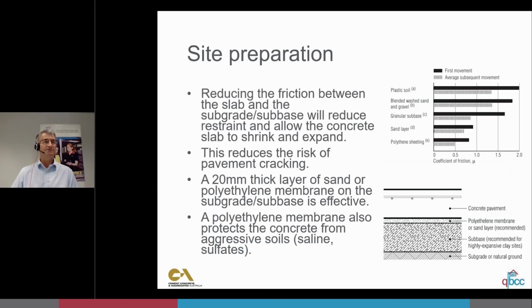And a few diagrams on this slide that just show subgrade, sub-base, and then a layer of sand or polyethylene. The polyethylene's quite good because it does reduce the friction between the concrete and the ground. So if the concrete can shrink in on itself, it won't crack as much.